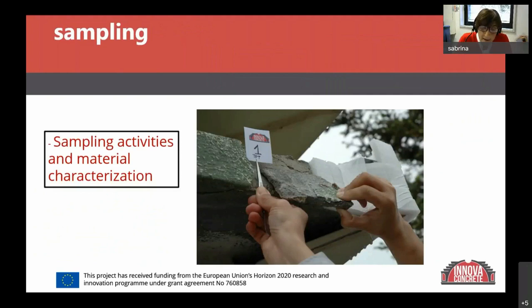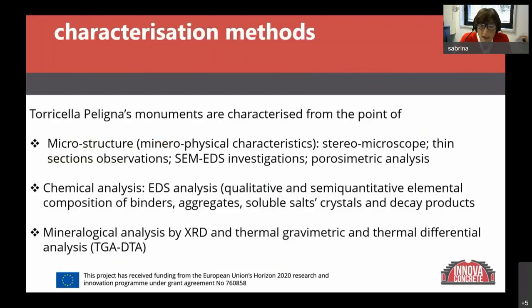The first step of our activity was the characterization of the material constituting the monument. A correct sampling plan addressed towards significant points allowed us to collect samples useful to investigate all the characteristics of the material, such as the microstructure, the porosity, the chemical and mineralogical composition, and the level of decay. The information obtained were used to reproduce laboratory specimens of mortars on which the product developed by the partners were tested before being applied on the monuments in situ.